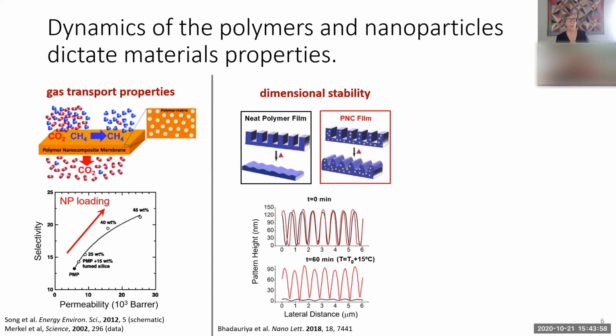Another example from imprint lithography is the flow properties. So here's an example where if you just have a neat polymer and you make fine lines, if there's a little bit of heat, it disappears altogether, but it's much more resistant to flow if the nanoparticles are there. And so these are just line traces across these different structures before and after annealing, right? So the nanoparticles add dimensional stability. And again, this is how the polymers and the particles flow. It's dynamics of that, which impacts this property.